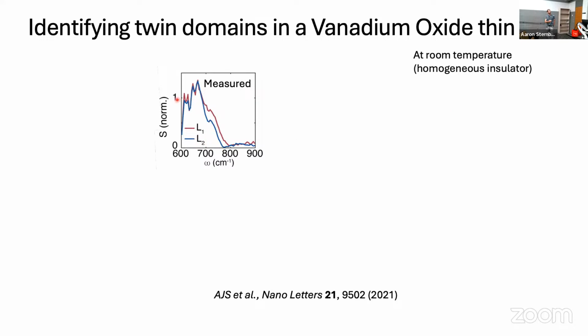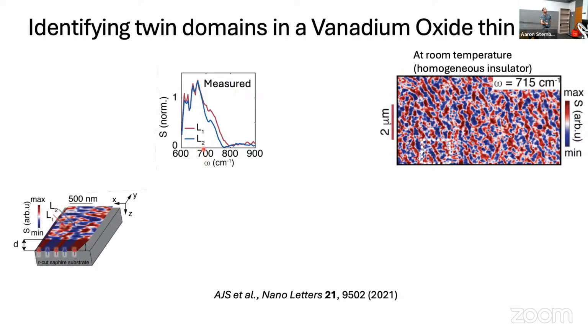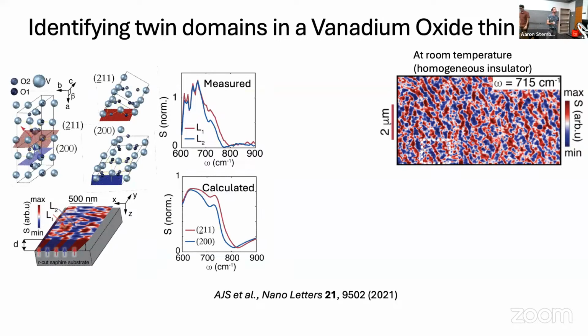So first, we wanted to look at spectra of the near field amplitude. And this spectra shows an edge at a frequency of around 700 wave numbers that comes from lattice vibrations in the system. This is a monoclinic phonon. We observed at room temperature, when the system is a homogeneous insulator, that there was an inhomogeneous phonon spectra. And if you park at a certain frequency around 700 wave numbers and take a map looking at how this contrast appears in real space, you can see these stripe-like patterns. Again, this is all at room temperature, where the system is a homogeneous insulator.